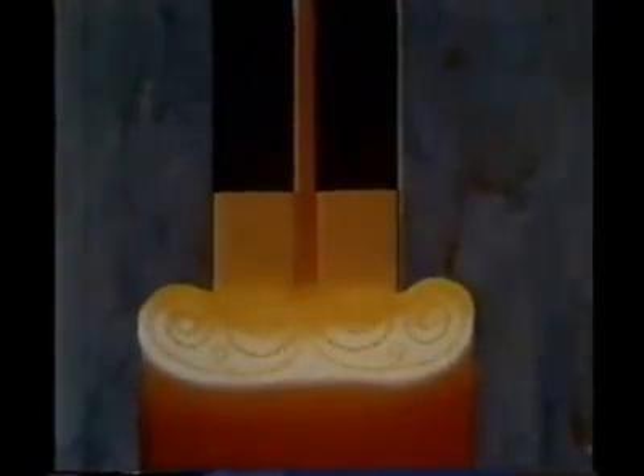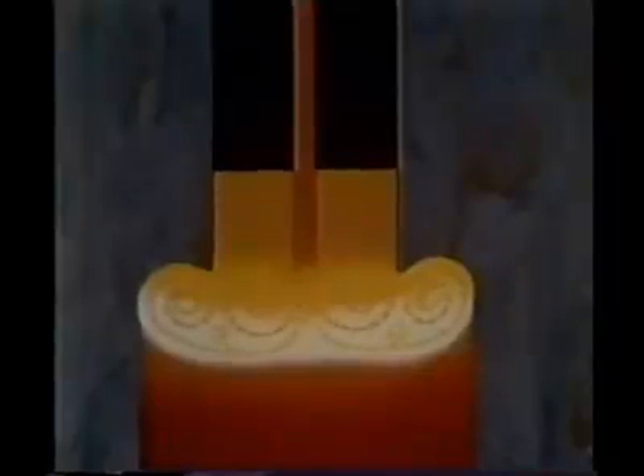Although this system is a direct development from established submerged arc processes, the arc in this case is extinguished 30 seconds or so after the start of the weld. From there on, the current between electrode and weld metal is transmitted through the slag, which becomes conductive. By this means, the slag is heated to a temperature well above that of the metal's melting point. In this way, the weld pool is maintained, both plate edges are well penetrated, and complete fusion throughout the plate thickness occurs between the plate edges during one single pass by the electrode.